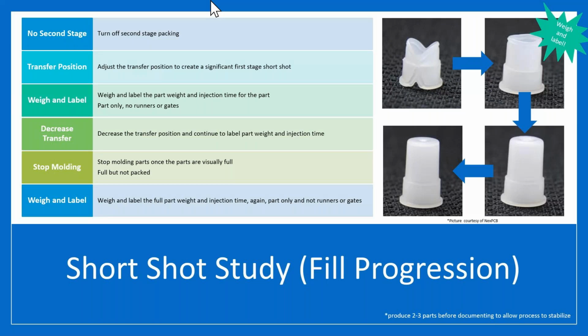We're going to mold that short shot. We're going to weigh it and label it, part only. And then we're going to decrease the transfer position and reiterate that same process. Shoot, label, weigh at varying percentages of fill. I like to do this at 10, 20, 30, 40, 50, 60, 70, 80, 90, 95 or 98, and 100%, so that you have a significant fill progression.